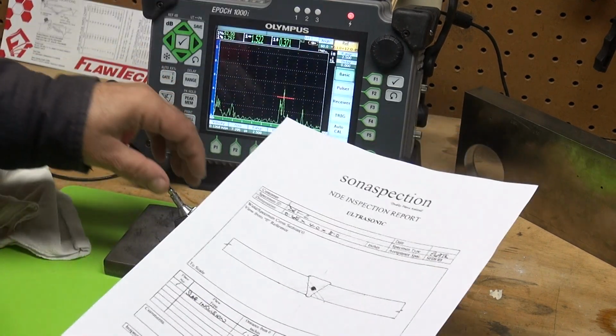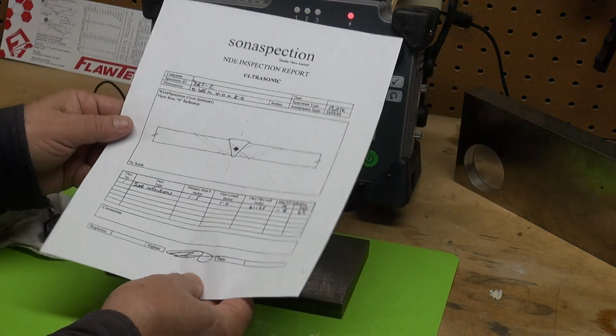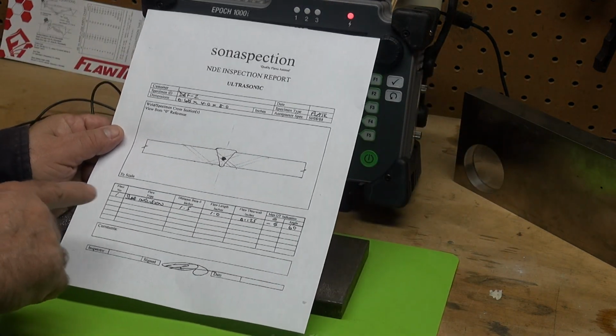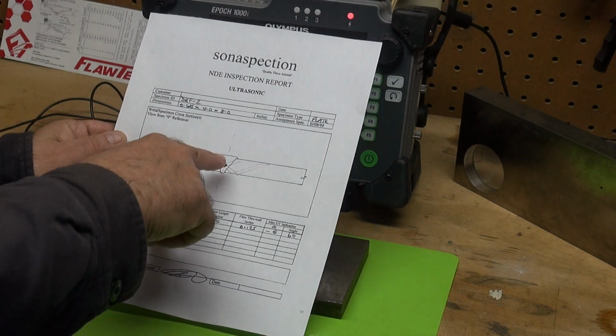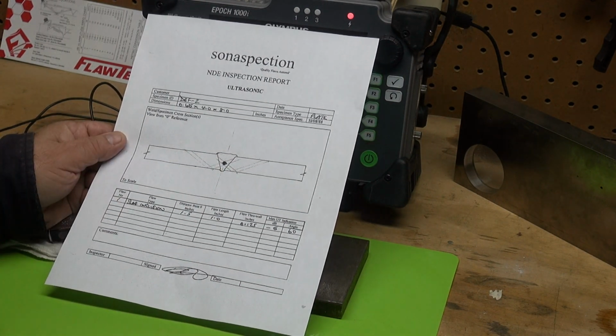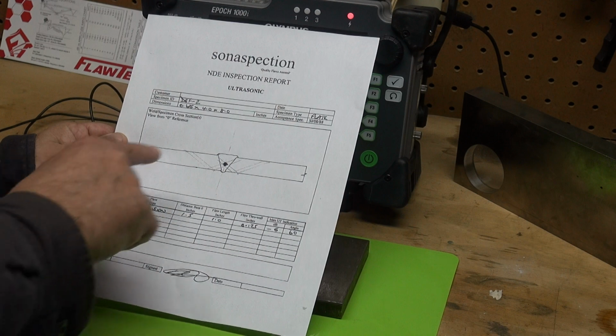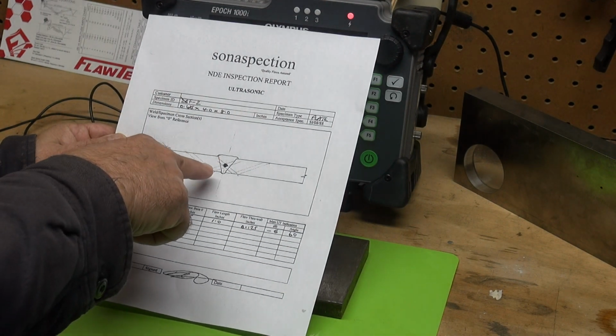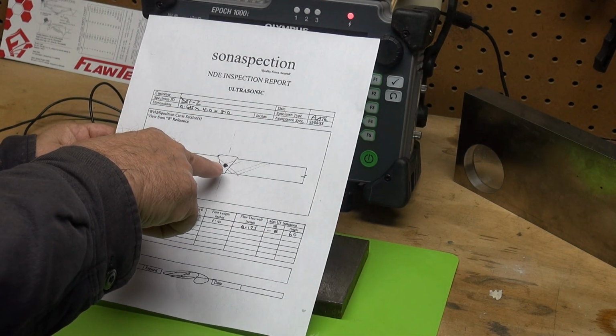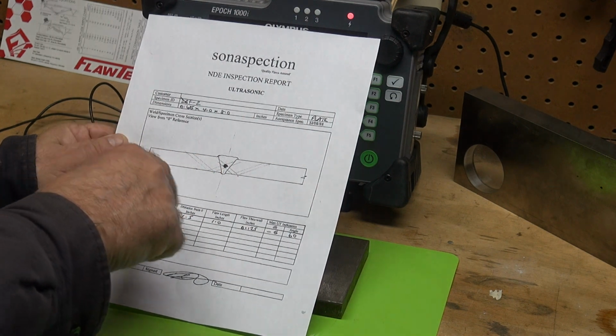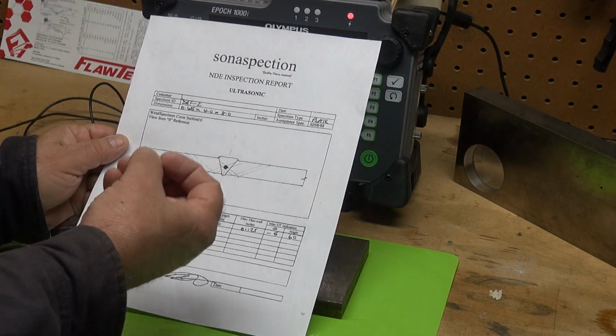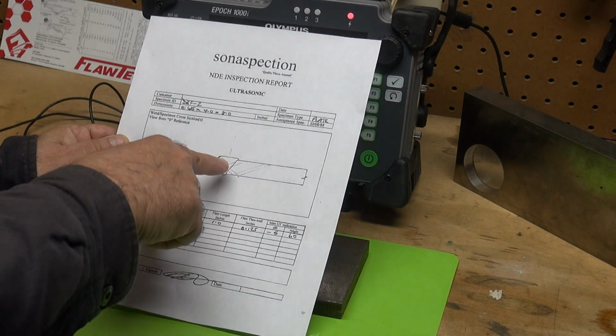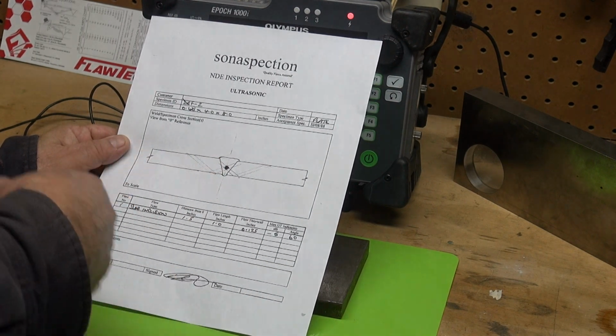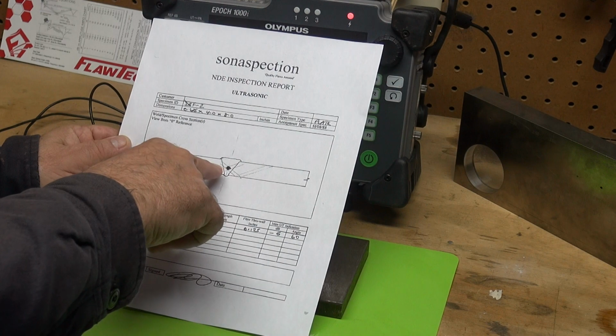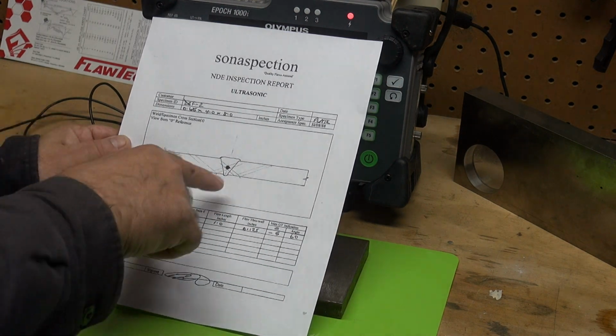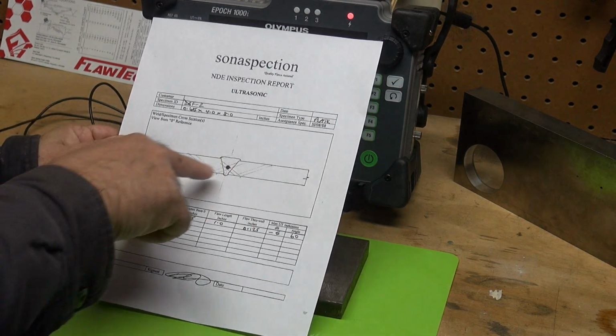Let's take a look at slag inclusion. This test specimen I have, this weld, has slag inclusion. And slag is a defect when a stick weld is used, shielded metal arc weld. It will leave a protective scab material, non-metallic material, on a weld. In between passes, the welder has to clean it out. If they don't, then it can entrap some of this non-metallic material in there.